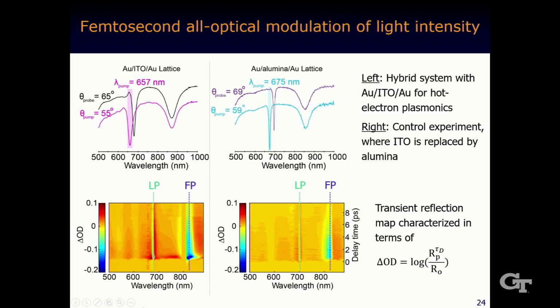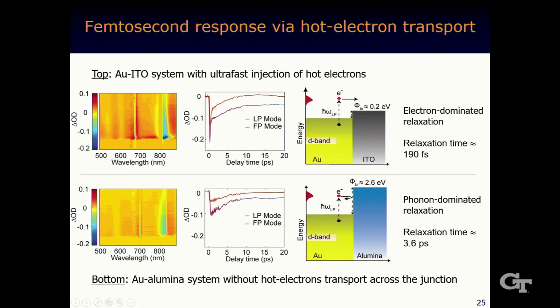Oh, by the way, we have two samples. One is based on gold and ITO, which facilitates the hot electron generation and transfer. For the other one, gold and aluminum oxide is used to replace ITO. In this case, they are not going to allow electron transfer because the Schottky junction will be extremely large. So the linear optical response is pretty much similar, and any response in the dynamic transient domain can be attributed to the material difference. From this nonlinear mapping, you can see the modulation is pretty pronounced at the resonance.